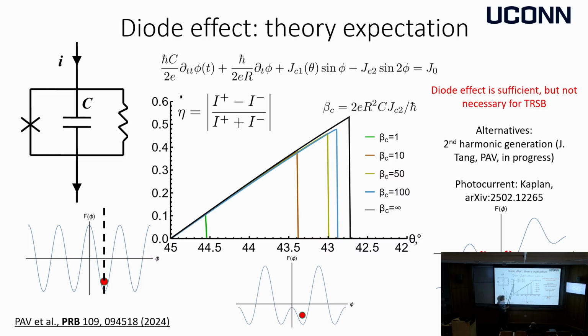So if you do the calculation, you find that not only at 45 degrees exactly the diode effect has to vanish. There's a reason for that, because at 45 degrees you just have the cosine 2φ potential, and if I sit in this well or that well, locally for this particle, left and right are the same. There is a reflection symmetry of this potential. This is not true here. For this particle, going to the left and to the right is different, but not in this case.